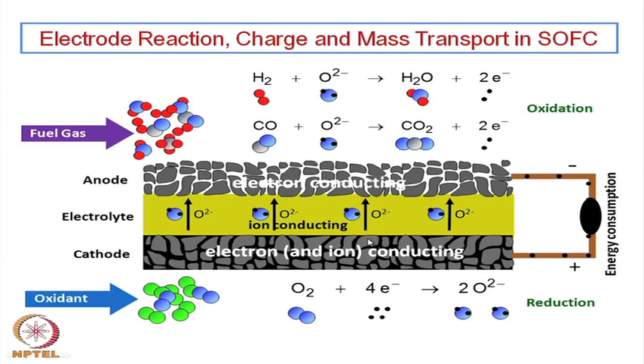So, the reaction sites are very important. Higher the reaction site, higher is the conversion, and better is the current carrying capacity or the current generating capacity. So, more electrons will be generated, and one can draw more and more current. So, it cannot be a completely dense material, it has to be a porous material, so that through the pores molecular diffusion takes place, oxygen comes to the surface, then gets atomized and it gets the electron and gets ionized. So, once the oxygen gets ionized, the electrolyte is specifically an oxygen ion conductor.